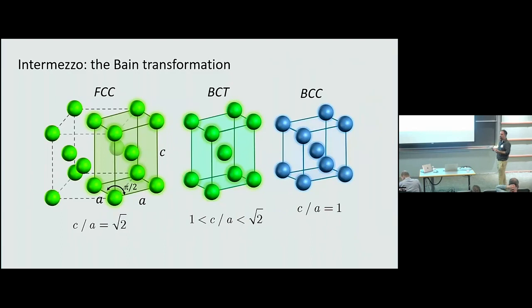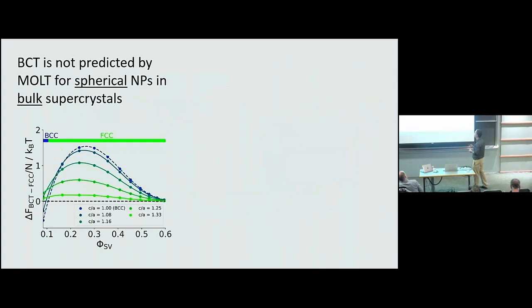Now the question is, if you look at the thermodynamics of the problem, does it mean that you have this as an intermediate, or it may just jump directly from FCC to BCC, because this is not thermodynamically stable. So that's exactly what we look at in theory. I did some calculations using different values of C over A that correspond to different BCT structures. And what we got was that none of those structures was stable in those conditions. Meaning that our theory predicted a transition from BCC to FCC, no stable BCT in between.